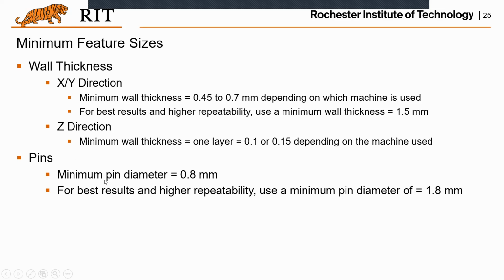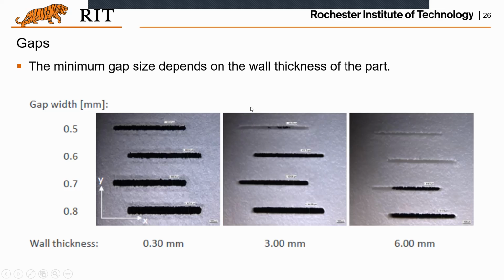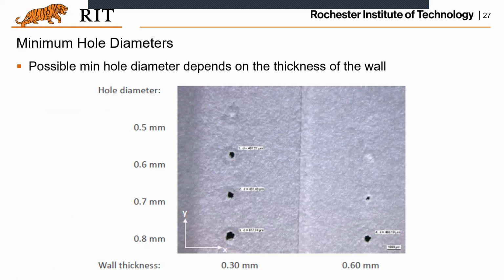For the pins, minimum pin diameter is 0.8 millimeter, but usually this is an ideal case. In order to increase the repeatability, 1.8 millimeter would be a better practice. So you can see if you decrease or increase the gap width, what it will look like for the prints, right? Same thing happens if you are decreasing the hole diameters, and it turns out there will be some failure starting from, I would say, 0.8 millimeter, right?